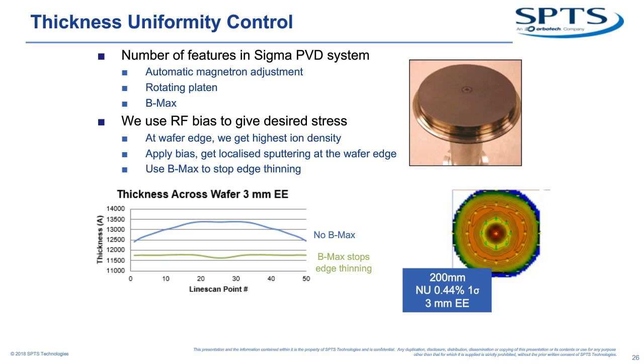Now, as I said before, we use RF bias to give a stress value. As we already said, at the wafer edge, you get high density, and when you apply bias, you get increased sputtering at the edge of the film, and the film actually gets thinner locally. We have Bmax hardware, and this hardware opposes the arrival rate of these ions and stops the edge getting thinner. So you can see on this graph down here, without Bmax, it's edge thin because the edge is being locally sputtered, but with the Bmax, it's very flat. Uniformity better than 0.5%, 1 sigma on an 8-inch wafer. That's great. So we have thickness control, very uniform thickness.